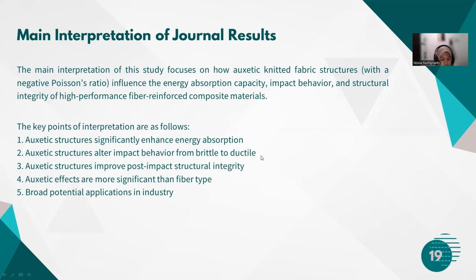Conventional composites exhibit brittle failure with rapid fracture after reaching peak load. In contrast, auxetic composites show a two-fold peak, or double peak, on the graph, indicating gradual deformation and more uniform distribution of impact energy. This phenomenon suggests that the auxetic structure helps delay damage and allows the composites to withstand much longer before failure. And auxetic structures improve post-impact structural integrity.